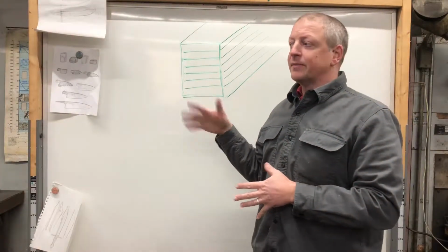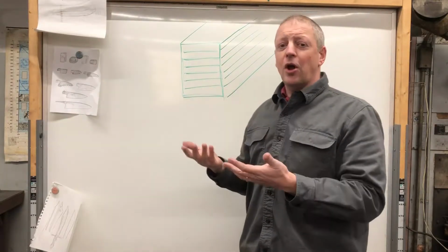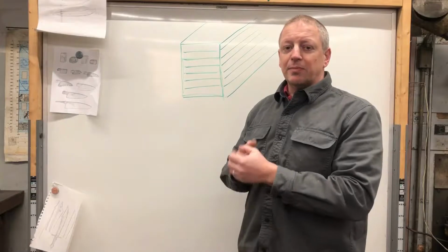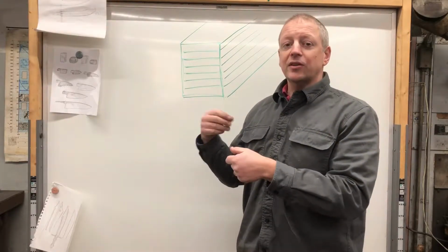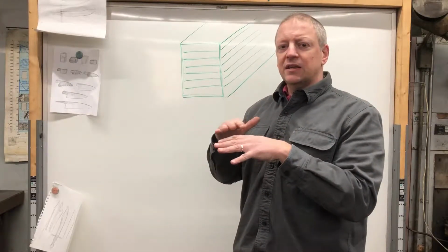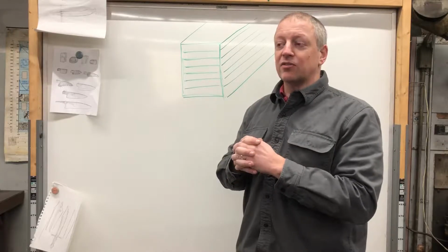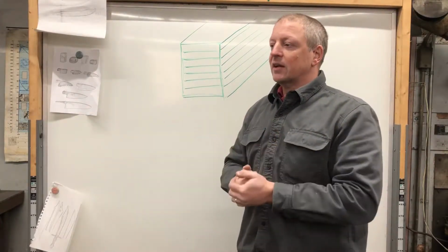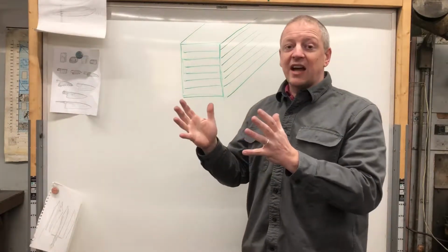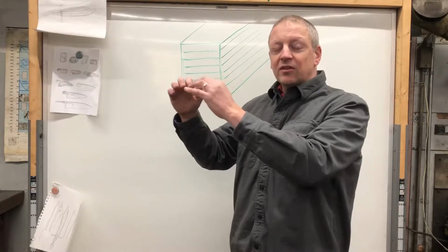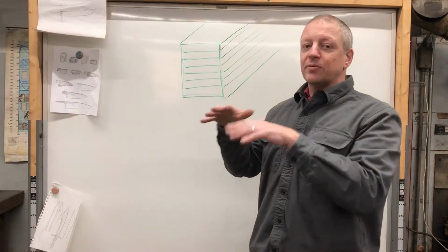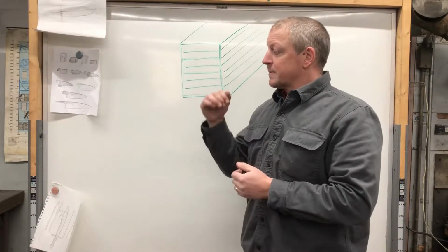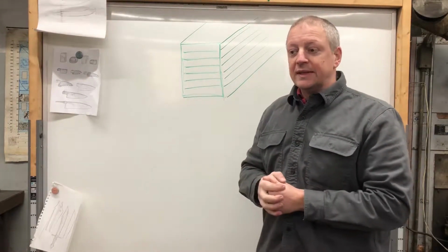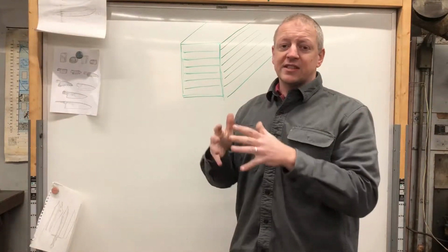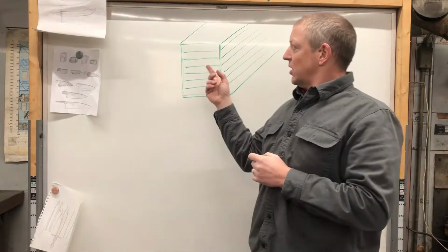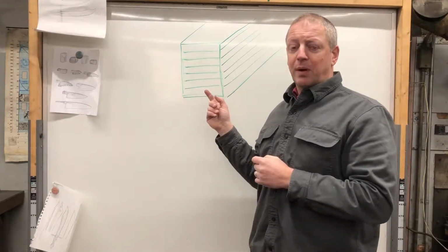But going back to the flux for a minute, those of you who have used flux on a billet know that when you put your billet into the forge, it's gotten moderately hot, you put some flux on it, and it melts on kind of like honey. And that's sort of the sign that things are moving in the right direction. It melts out onto the surface, it coats beautifully, and then the sign that it's working is that you start to get those little dancing bubbles. Particularly, some everywhere, but particularly at the junction of the layers, at these seams. Now, what we've always been told was that shows that the flux is active. I don't think that's true. I think what you're seeing is the carbon monoxide bubbling out.